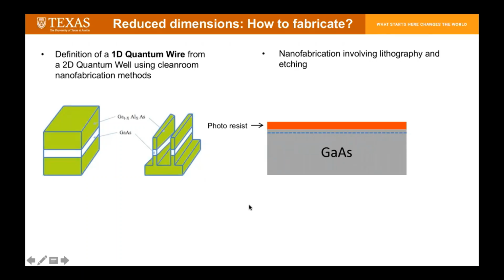You'll spin coat this substrate with photoresist if you want to do photolithography, or PMMA if you want to do EBL, electron beam lithography. And you pattern the photoresist using a chrome-plated photomask. You expose the unmasked regions of the photoresist with UV rays, followed by development. So whatever was shown to UV light has been developed away. You basically form a mask of photoresist, and you can then etch away the gallium arsenide in these regions. So you see the gallium arsenide has been etched in these regions.